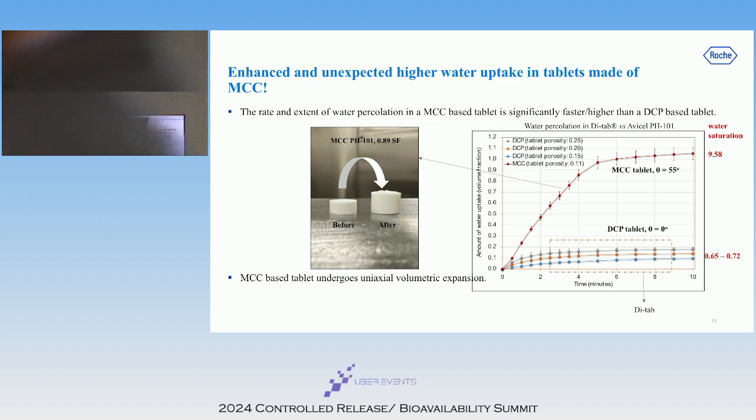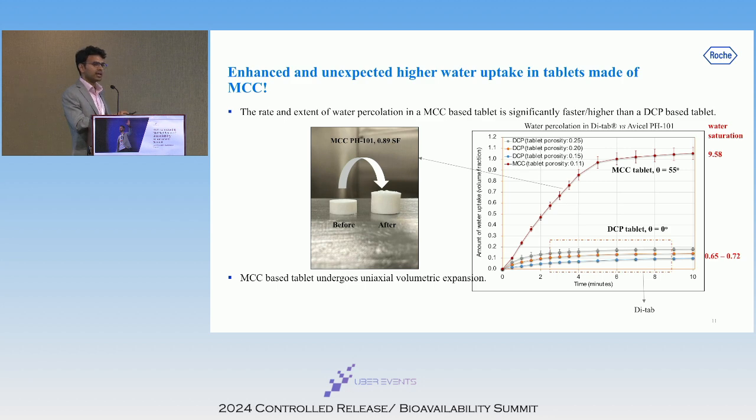The second observation that we saw was the volumetric expansion of the MCC tablet before and after the water uptake study. We believe that as the water is ingressing into the MCC tablet and it is volumetrically expanding because of the swelling behavior of MCC, it's creating more pores, and that is helping facilitate more ingress of water into the MCC tablet. This may perhaps suggest why we saw such enhancement in the disintegration performance in the earlier case study.